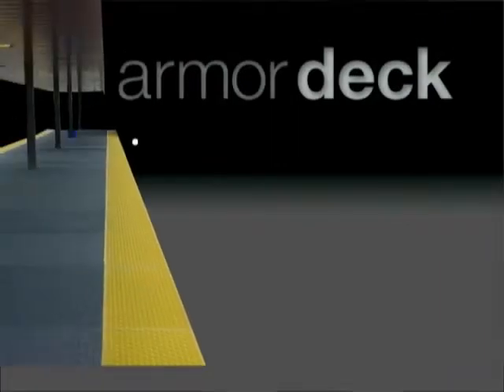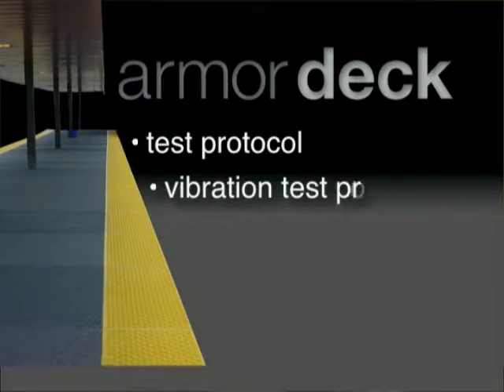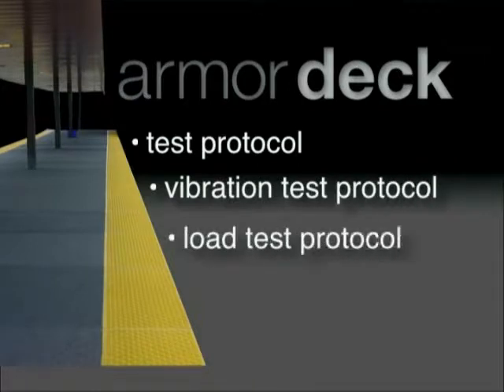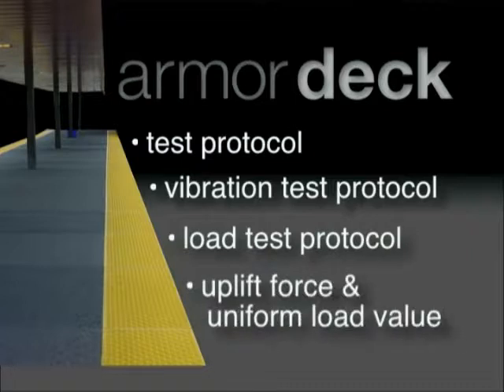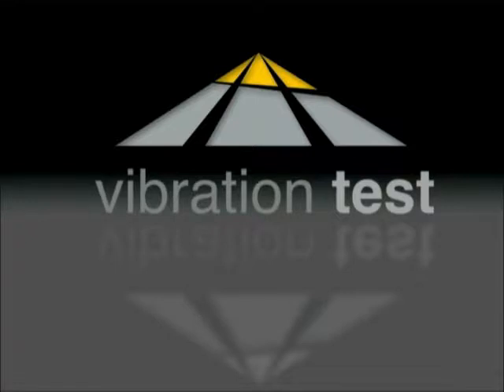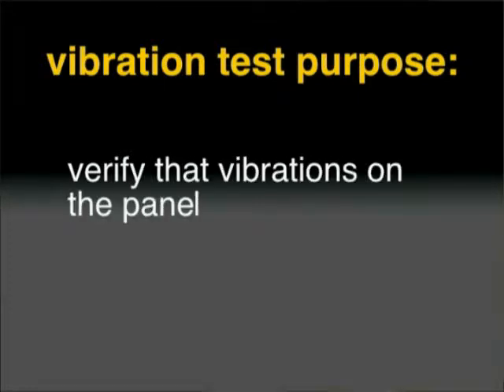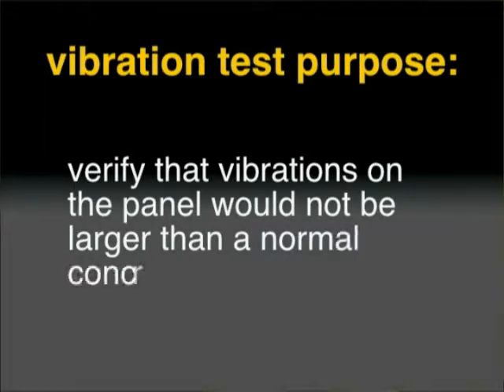We developed the test protocol, and we developed the vibration test protocol, the load test protocol, the uplift force, and the uniform load values. The first test that we did on the armor deck panel was a vibration test. The purpose of the vibration testing was to verify that vibrations on the panel would not be larger than anticipated on a normal concrete panel.